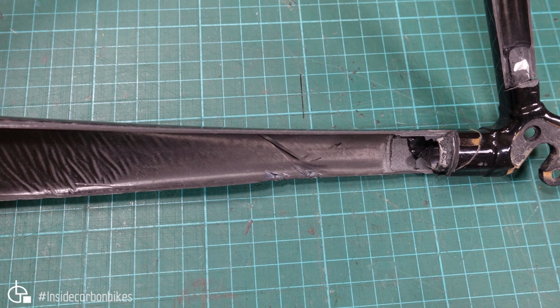So here we have that delamination, and you can also see some corrosion and some delamination around here. That's due to these little rivnuts in there, which the cable guide screws onto. If you're running an electrical groupset, you can remove that, so you don't have this big cable guide sticking on the underside of your chainstay, but if you're running mechanical, then you obviously need that. So there's some damage done during the drilling process.